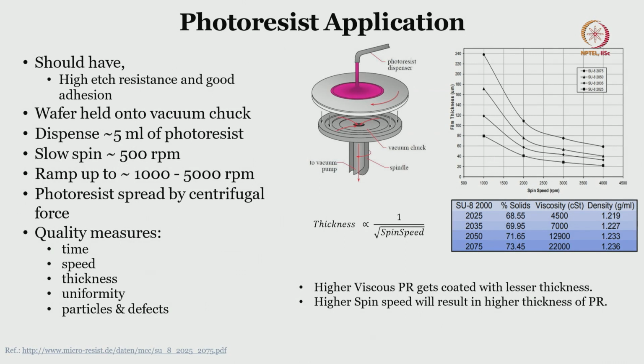How we should use a photoresist, like I said, these are some of the ways to use it. We already have seen how the photoresist parameters should be. This particular image will help you to further understand that there is a spindle, there is a vacuum chuck here, and then a vacuum pump is there. So, the spindle will rotate, but because the wafer is held to the vacuum chuck, the wafer will not fly, and you can dispense the photoresist, about 3 to 5 ml. Then you can see that as you increase the spin speed, the thickness of the photoresist starts decreasing, so that at a higher spin speed or higher RPM, the thickness is lower. And further, if you want to really understand, the thickness is inversely proportional to the square root of the spin speed. A more viscous photoresist is coated with greater thickness, and a higher spin speed will result in lower thickness, right. This is obvious.